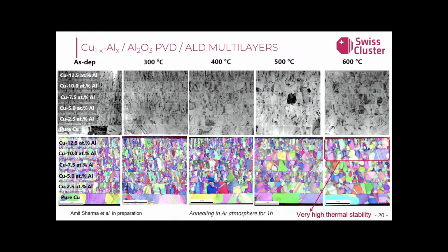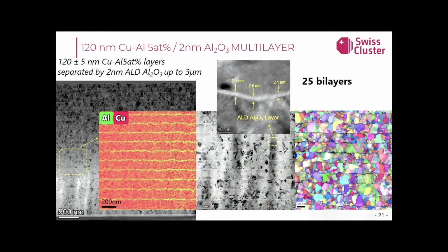We also do annealing to assess the reliability of the film at higher temperatures. We see that even at 600 degrees, we have prevention of grain growth because of the ALD layer. So we take the copper aluminum 5%, and every 120 nanometers, we introduce 2 nanometers of aluminum oxide deposited by ALD. You can see how the aluminum oxide by ALD conforms along all of the surfaces of every PVD layer. This passivates surface defects and provides this glue to maintain the mechanical reliability.